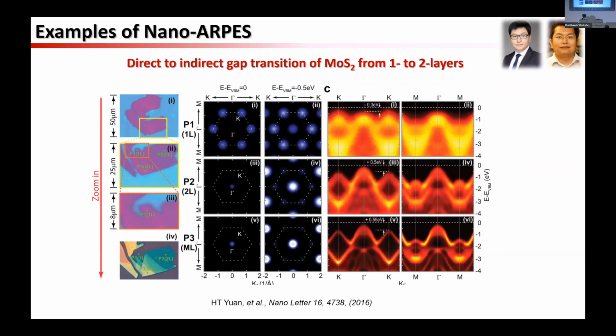Now, besides graphene, we also tried to work on TMD materials. This was early work, in collaboration with Hongtao Yuan and Xiaodong. You can see that we were able to image the photoemission intensity map, and see this flake clearly, and the flake shape corresponds to the optical microscope image. So we were able to identify the positions where we have 1 layer, 2 layer, 3, or even multiple layer regimes. Then we focused the beam on the different layers. For 1 layer, the valence band top resides at the K point, and once it becomes 2 layers, the valence band top shifts to the gamma point, which causes the direct to indirect band gap transition. But the 2 layer and multiple layer don't really have a qualitative difference, only a quantitative difference.